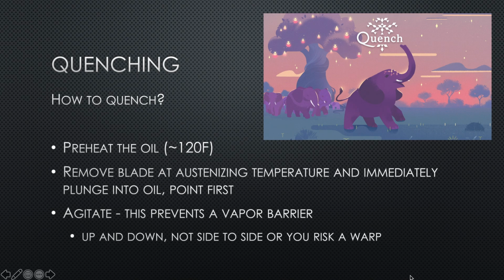You're going to remove the blade from the forge or the oven, and you're going to plunge it directly into the oil, usually point first, and agitate it, meaning move it around. This will prevent bubbles and things from forming around the steel and preventing more cooling. So you want to continually get fresh oil, so to speak, around your blade as you're moving it up and down. And you want to do up and down, not side to side. Side to side, you risk warping your blade.